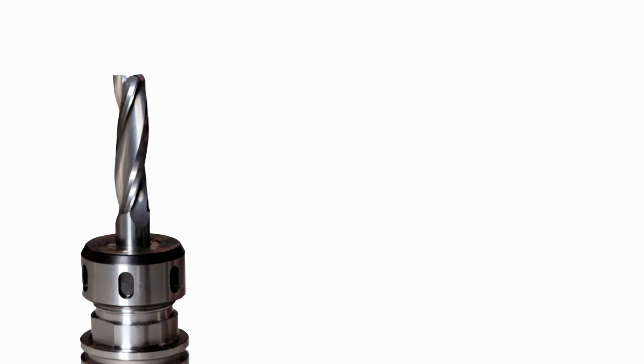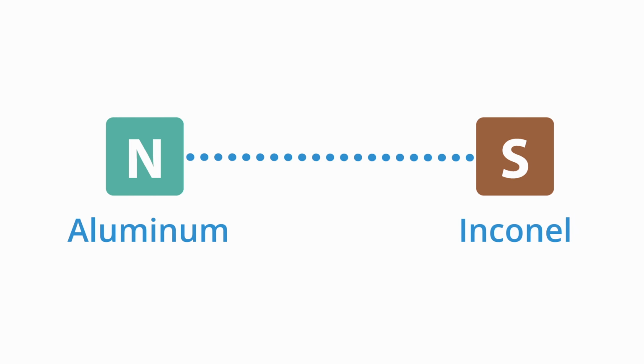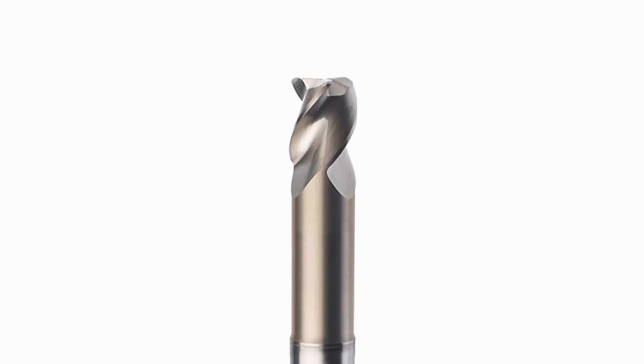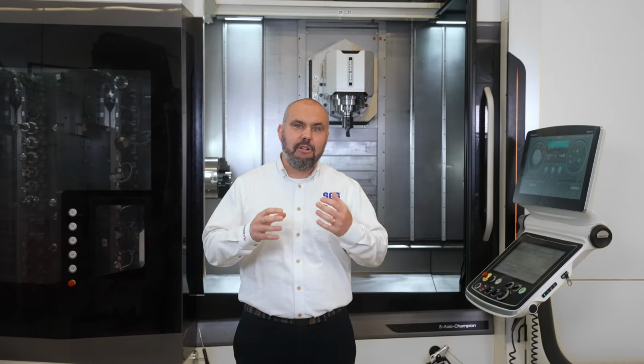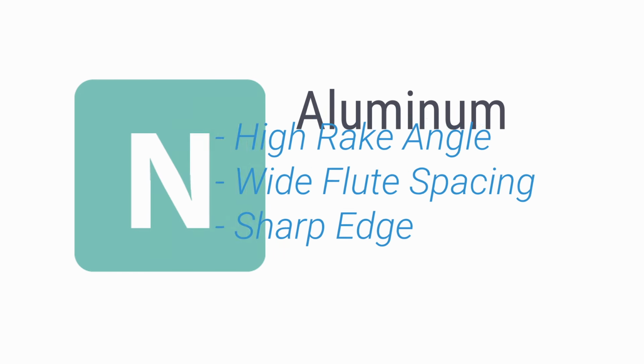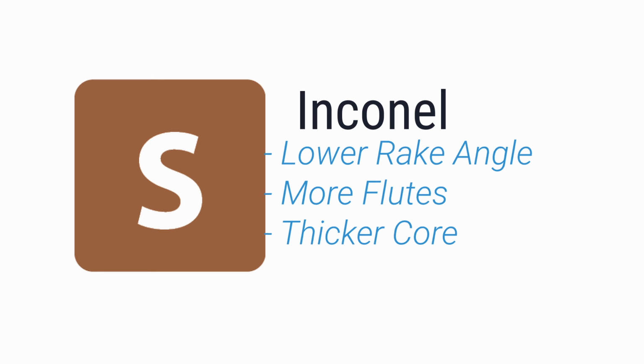So back to the big question: can one solid carbide end mill handle materials that are extreme ends of the machining spectrum, such as aluminum and Inconel? In a pinch, yes, but it won't do either of them well, and it's not something we'd recommend. Geometry matters, and when you look at it closely, it tells you everything you need. High rake angle, wide flute spacing, sharp edge, that's an aluminum cutter. Lower rake angles, more flutes with a thicker core, that's a tool for Inconel or other similar materials. Don't fight the machine, don't fight the material, and definitely don't try and fight the tooling. Read the geometry and let it guide you to the right decision.